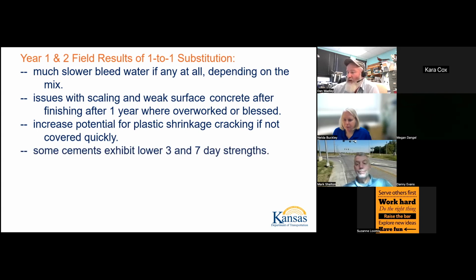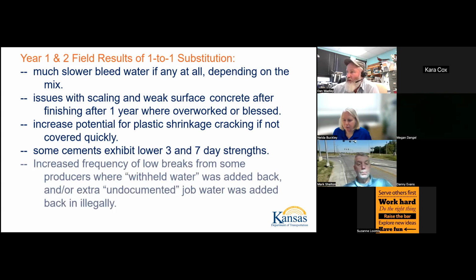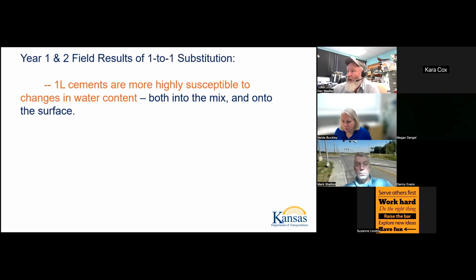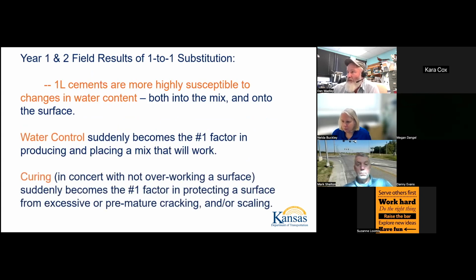Increase for plastic shrinkage cracking if a good curing regime is not followed. Some cements do exhibit different strength gains, especially early, most predominantly early, before 7 days. We've seen an increased frequency in low breaks, but as we talked about in some of the other previous discussions, that's not all to do with the cement. A large part is due to water that's being added back at the job illegally or not controlled at all during the batching. And so it kind of leaves us with this situation where water control and curing are very important when using a 1L cement.